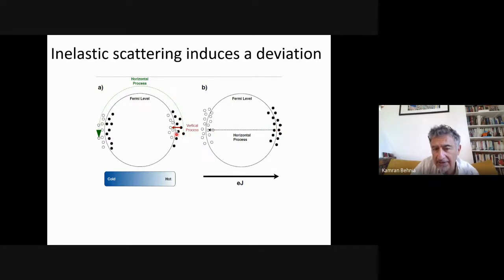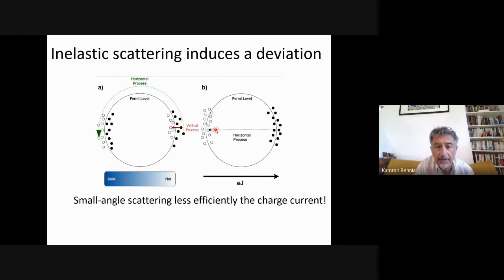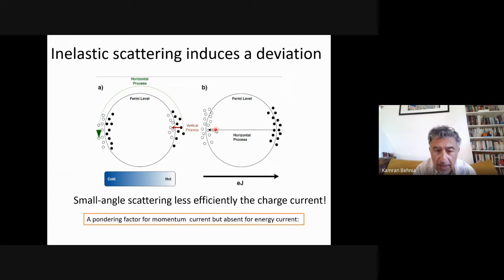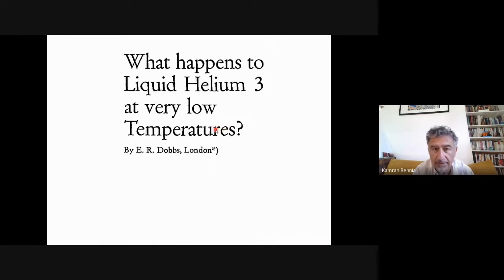So this small angle scattering, which occurs when a carrier of heat is scattered in a way that it just drops across the Fermi level, is not operative here. For having an electrical resistivity, you should think of an event which actually brings an electron from this side of the Fermi sea to this side of the Fermi sea. And because of this, a small angle scattering is less efficient for the charge current, and there is a weighting factor for momentum current, which is absent for energy current. So this has been the traditional way of understanding why the two slopes are different.